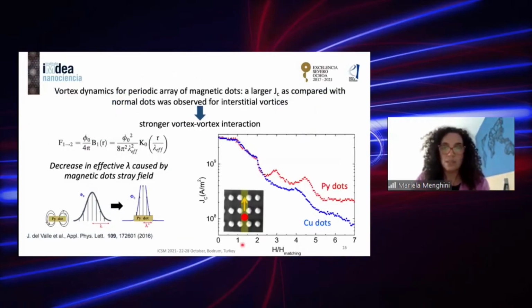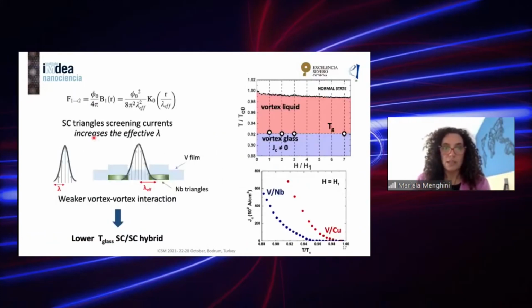the system. So to try to understand that, we went back to some previous results on arrays of magnetic dots, where a larger critical current was observed also for the case of interstitial vortices. So this is permalloy dots on niobium film, and when you compare the critical current of the permalloy dots, again as a function of field, it is larger than the case of copper. So the argument here was that due to the stray field of these magnetic dots, there is a decrease of the effective penetration length, and that decrease in the penetration length causes a stronger vortex-vortex interaction.